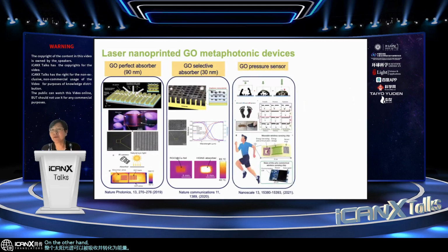On the other hand, graphene can also be made into sensors because of the electronic properties. So in that case, we made this kind of pressure sensor using this broken bridge structure. And this structure is allowed to detect pressure with very high sensitivity. So the ultimate goal for us is using a single graphene film. So we are able to pattern different devices. So for example, this one is the wireless communication device, RFID basically. And then the second is the energy storage device, which is a supercapacitor. And then the last one is a sensor.